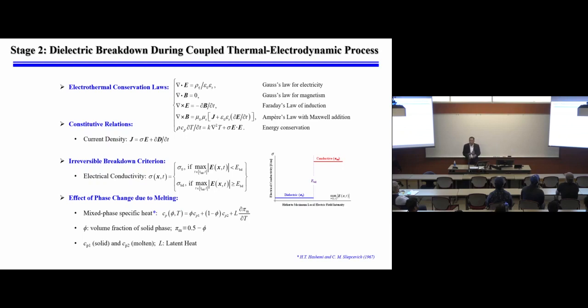And then you have a breakdown model as well, in the sense that initially the polymer is not conductive. Only the polymer goes breakdown, by the way. The metal does not. So the polymer initially is dielectric, is not conductive. And so we have a model that says that if the E-field is small enough, the material has very low conductivity. By the way, the theory says that even for dielectric materials, you have a very small amount of conductivity. It's so low that it's probably practically undetectable.